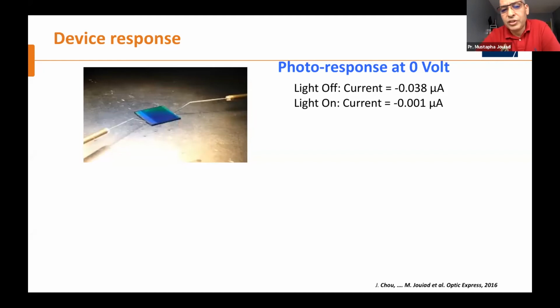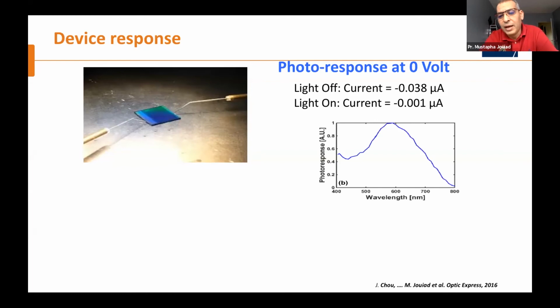So now to test our device, here we put a very simple way to test it. What we did, we just made it at 0 volt, and we tried to put light on and light off to see. And of course, we did it at different wavelengths. We have the maximum response in the visible range, and we have the current occurring when we shine our device with the visible light. And this is interesting because we moved it from UV to visible light.